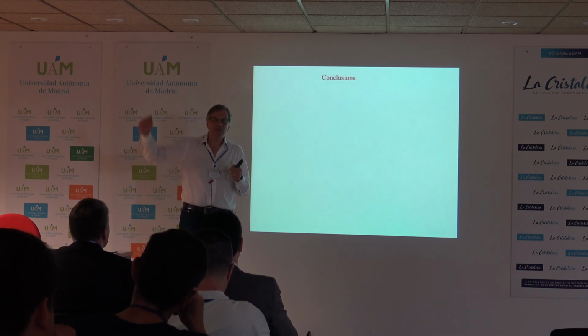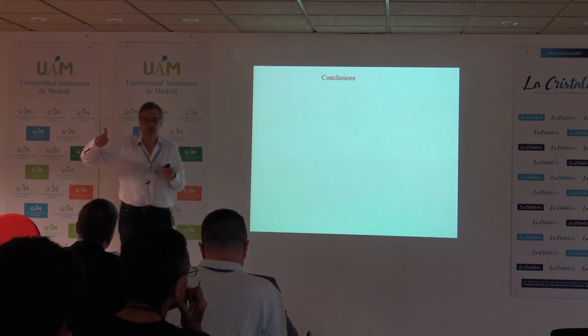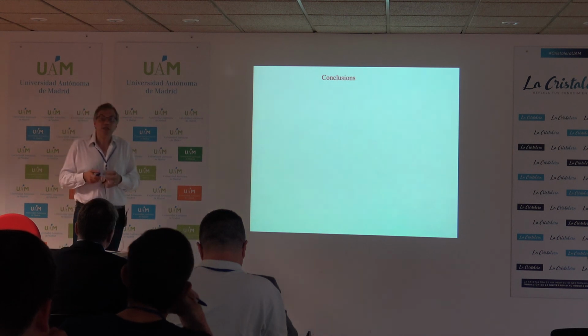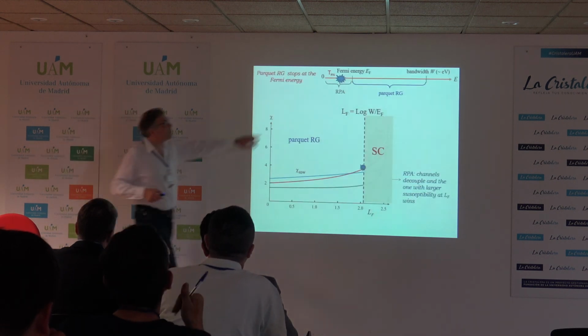This RG approach tells you one simple thing, that at the end of the day you start with attractive interaction in the spin density wave channel. And you ask how it affects superconductivity and orbital physics. And you can start with repulsive interaction in the superconducting channel, and find out that because the system tends to develop spin density wave, it also converts repulsion into attraction. And you can stop there and say, okay, this means that I get attraction in the superconducting channel, the system has strong magnetic fluctuations, so let me move on and study the electron-boson problem, which will be a perfectly okay thing to do. Or you continue with RG, saying that I'm still at weak coupling, but I want to play the game with logarithms, etc. Of course, RG is not the full story, absolutely not. RG requires separation of scales.